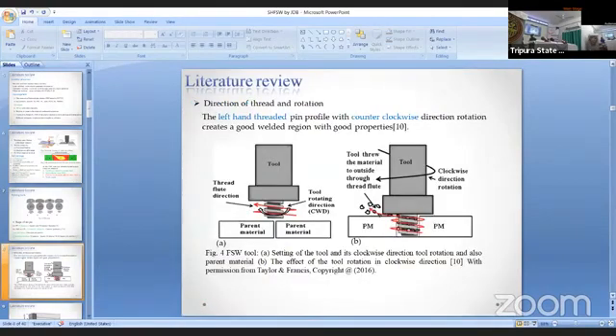Now, direction of thread and rotation also plays an important role. So the left threaded pin profile with counterclockwise direction rotation creates a good welded region, of course, with good properties of weld. So as you can see in this figure, that is the setting of the tool and its clockwise direction, and also the parent material. And in B, you can see the effect of the tool rotation in clockwise direction. Okay. So what happens, the tool throws the material to outside through the thread that is present on the pin.